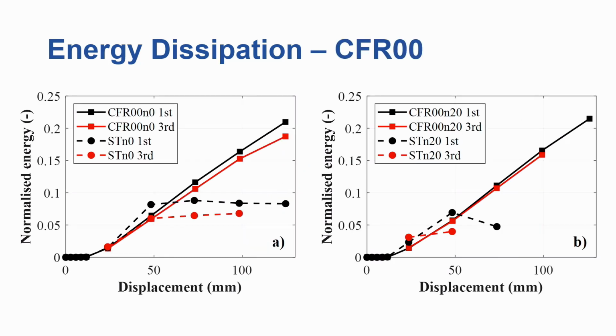So the black solid line is the energy dissipation from the first cycle at a given displacement level, and the red line is the energy dissipation from the third cycle, which just shows the degradation in the material. So these are the results on the left for the specimens subjected to a 0 axial load level, and on the right for those subject to about 20% axial load level.